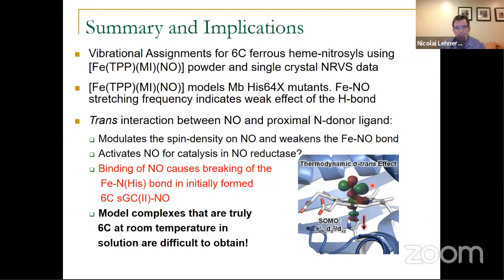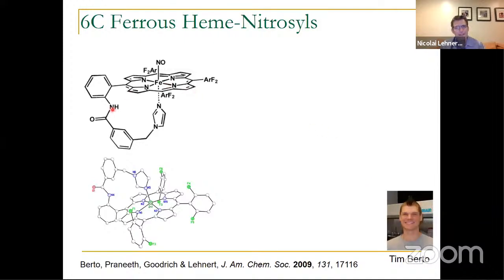So one of the other aspects then is, because imidazole binds so weakly to iron, it is actually challenging to make these 6-coordinate complexes in the model system, and you have to add a large excess, usually, of the axial ligand in order to form these kinds of complexes, because their binding is so weak because of this sigma trans effect. But you can help yourself out then by making constructs like this, and this is something that we did in my lab. We made this complex where we attached our imidazole group to this tail.